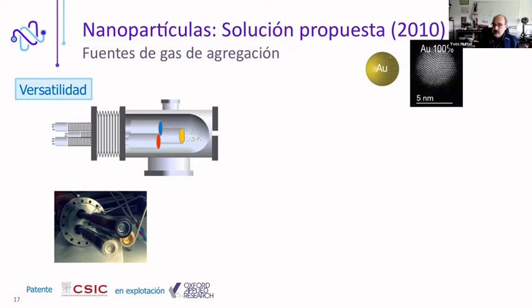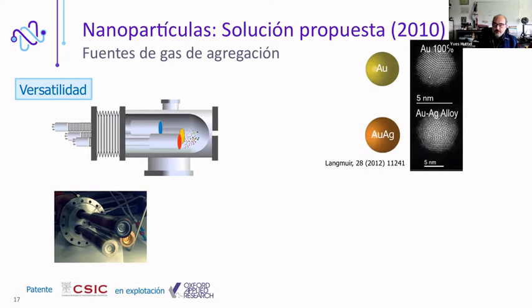As you can see, we were able to make gold nanoparticles with a high crystallinity. When we wanted to make alloyed nanoparticles, we put the two magnetrons at the same distance in such a way that the plasmas of the two magnetrons could mix and form alloyed nanoparticles like this one, a gold-silver alloy nanoparticle.